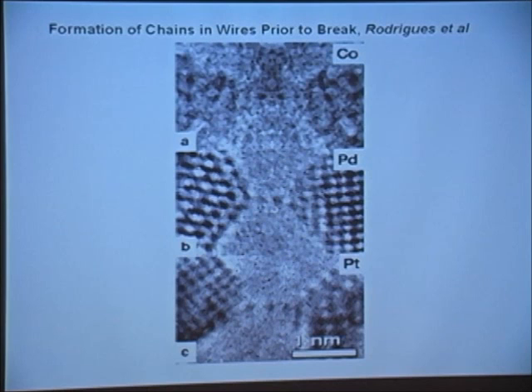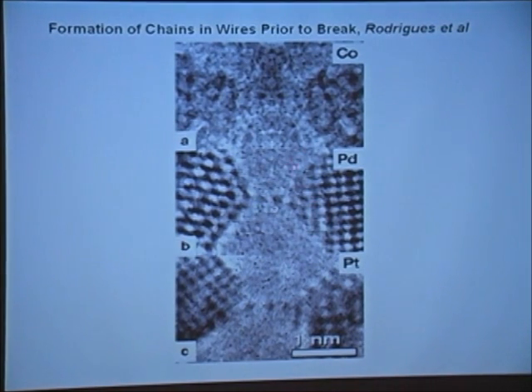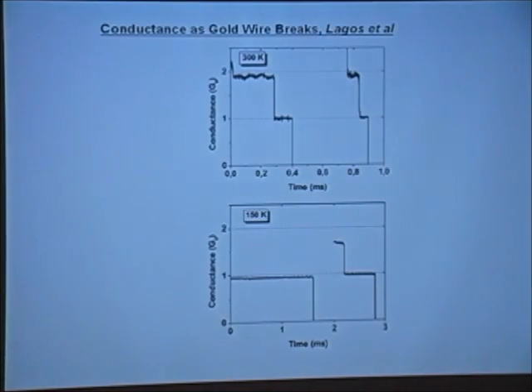Unfortunately, this is not very good because it hasn't come out very well. This is from a paper in which people had looked at the structure of the wires. It hasn't reproduced very well actually, but this is cobalt, this palladium, this platinum. Basically, just before it snaps, there are filaments which will give rise to the quantized conductance. The filaments are one atom wide, and there's a number of them, and as we pull it, they snap. And we start to get the quantized conductance.